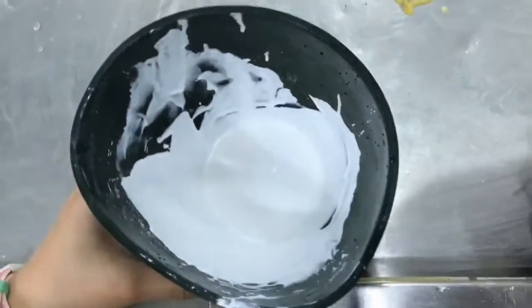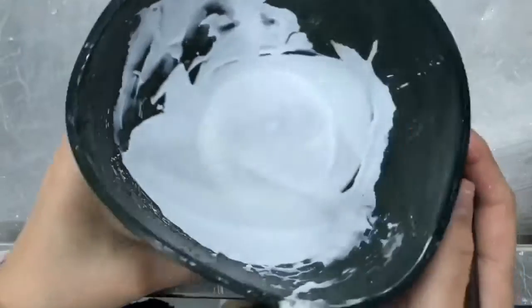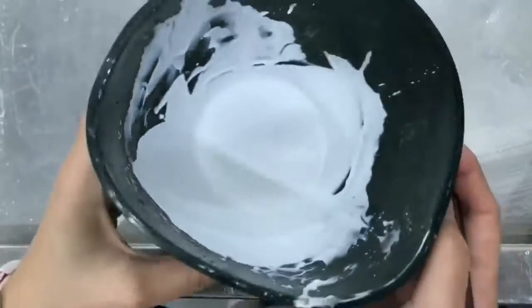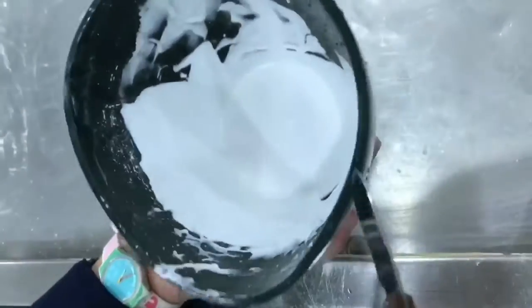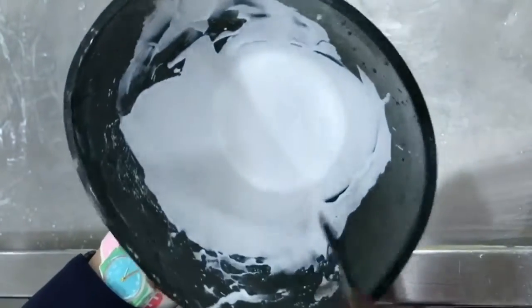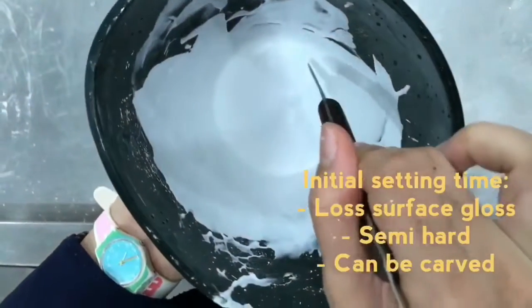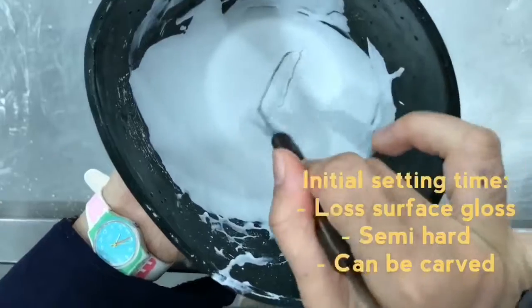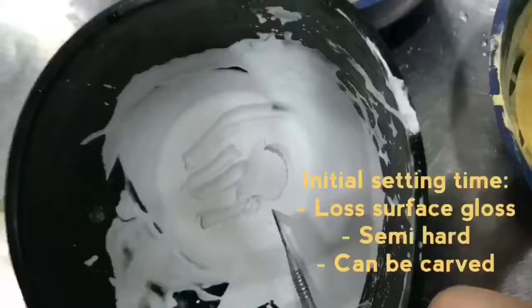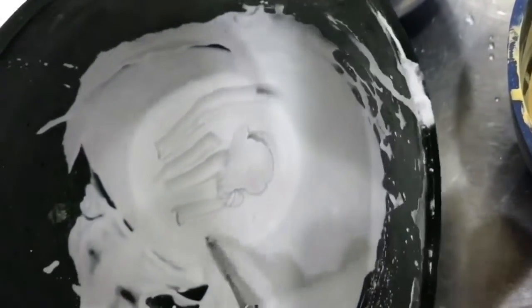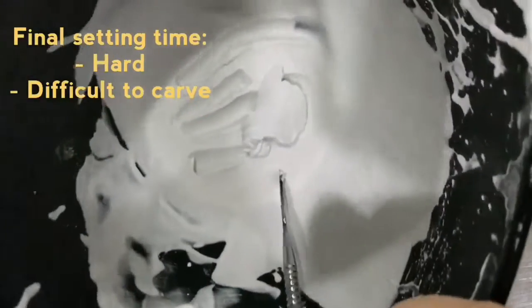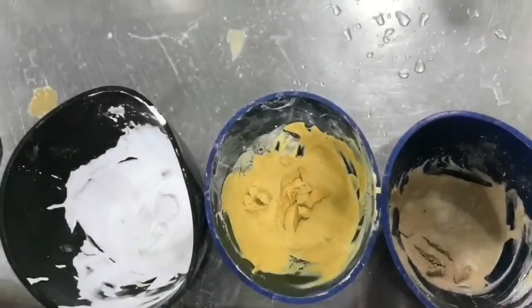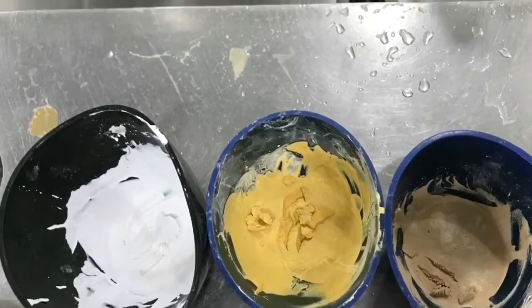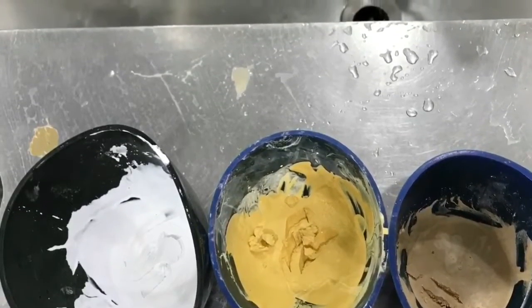During the initial setting time, we can see that it lost its surface gloss and it is semi-hard and still can be carved. And during the final setting time, it is hard and difficult to carve. This is the appearance of the three materials after the final setting time.